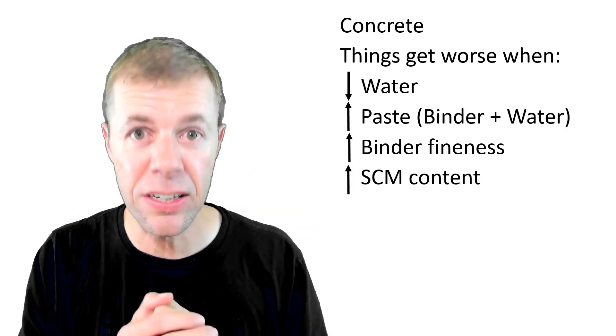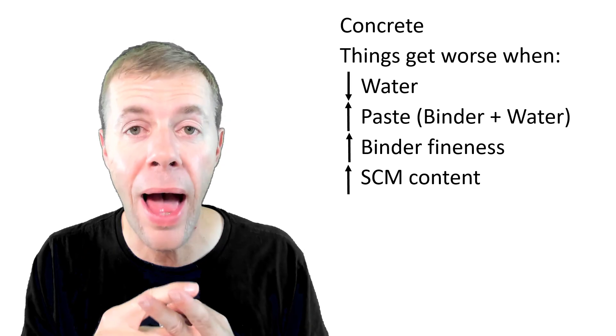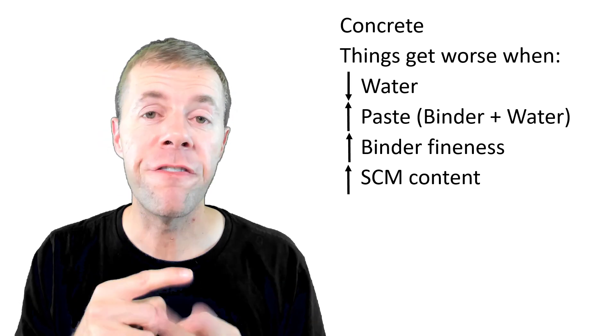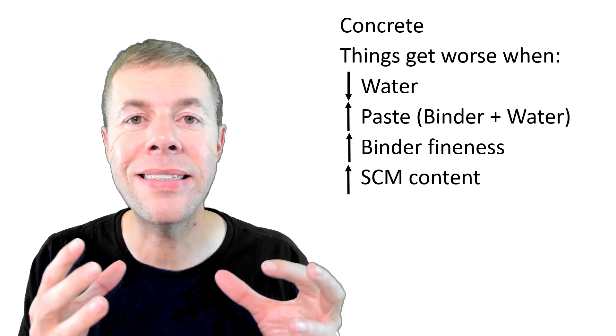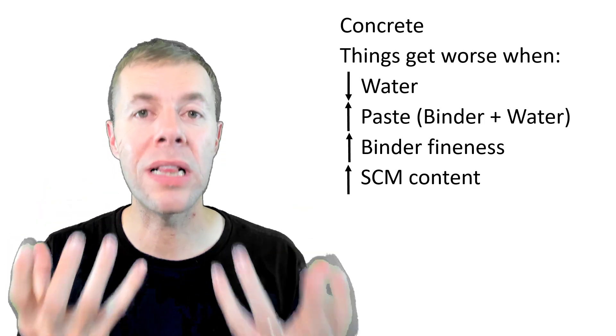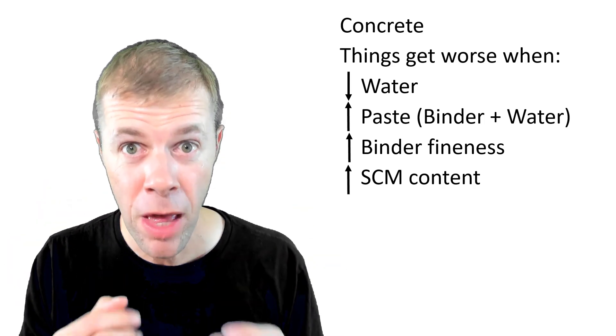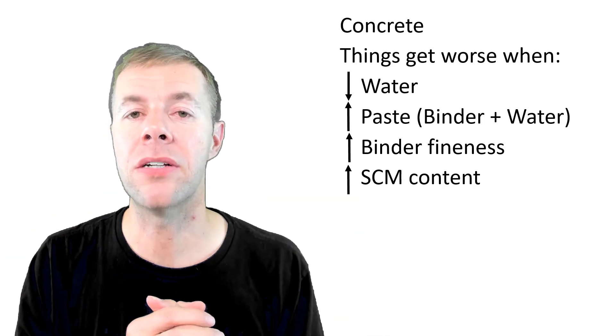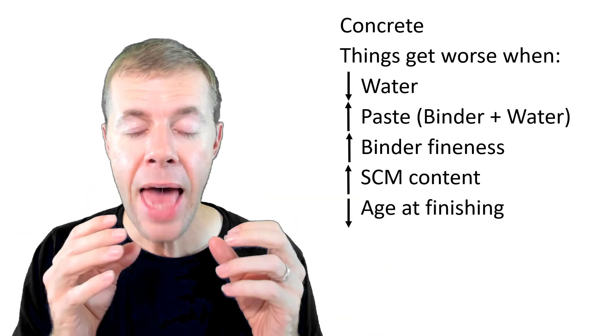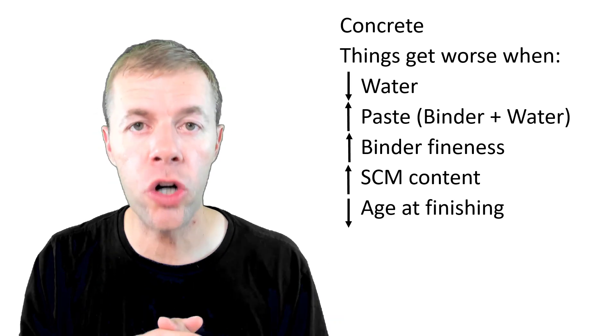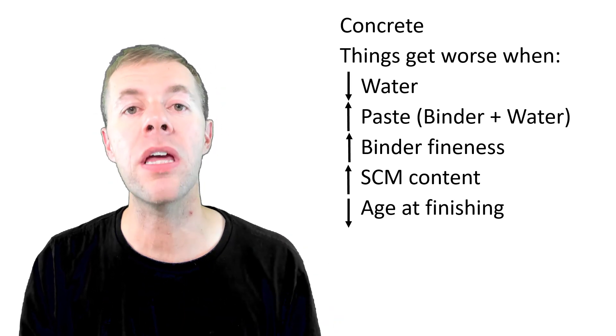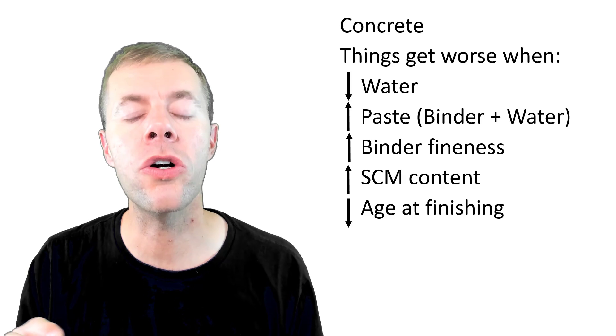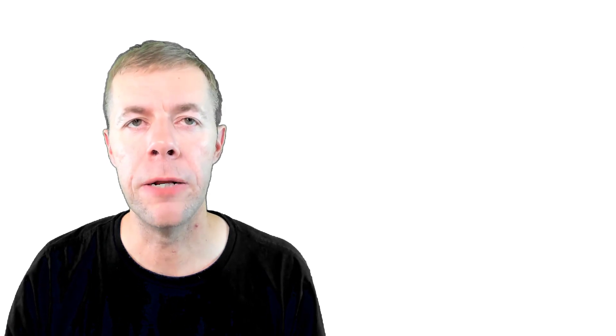When we have high amounts of SCMs like fly ash and slag or silica fume, the fly ash and slag will delay set and it makes it more likely for this to happen. Silica fume with that high fineness sucks up all the water and makes this more likely to happen. And if we finish and strike the concrete off very early, it will give it a longer period when this can happen.